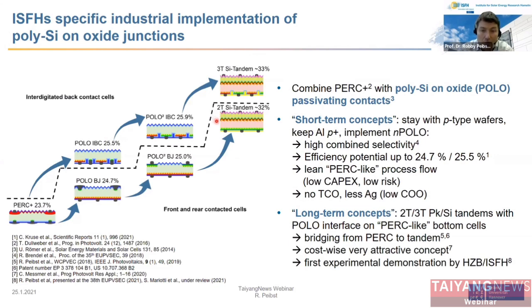And here we have proposed to use this polysilicon oxide junction as an interface between the subcells of the crystalline silicon bottom cell and the perovskite top cell, either in a 2-terminal monolithic configuration or in a 3-terminal monolithic configuration. And quite recently, we have also demonstrated the first proof-of-concept device.